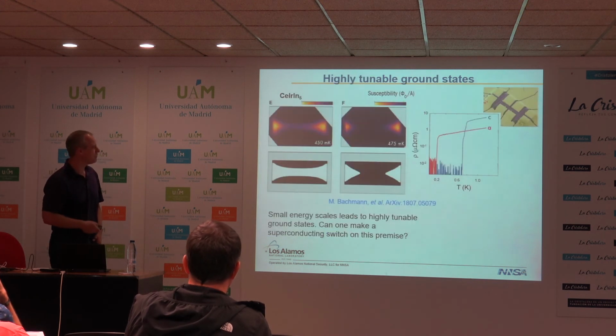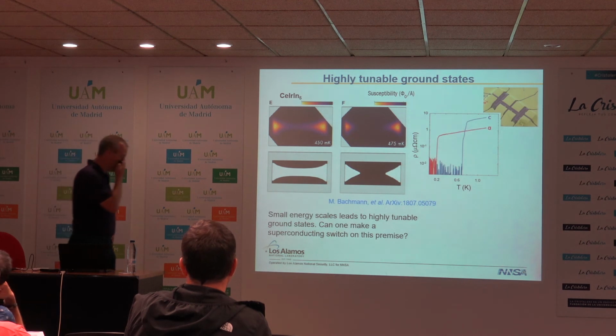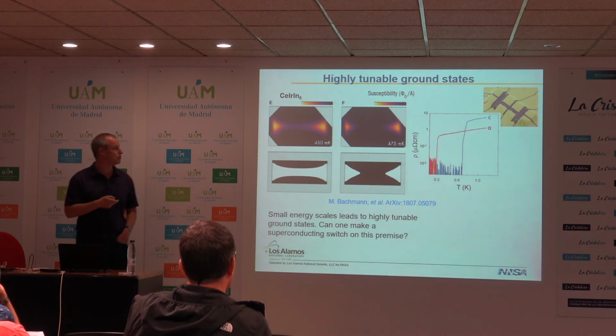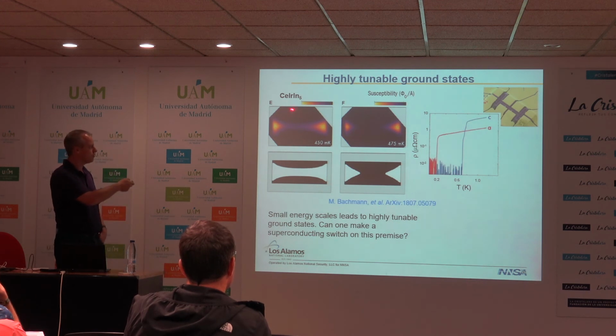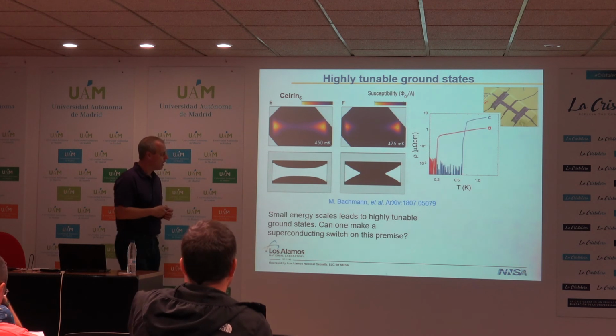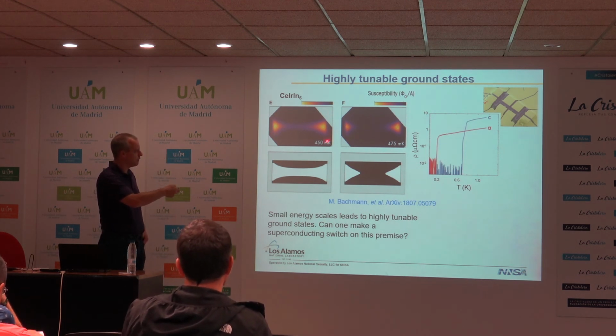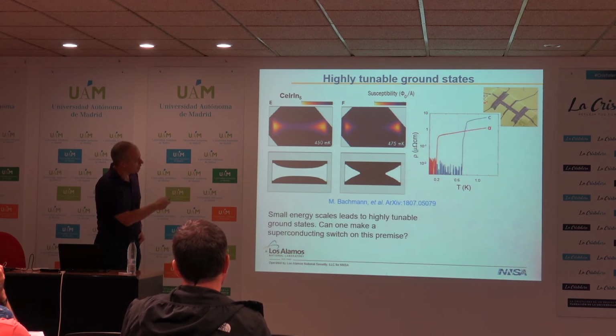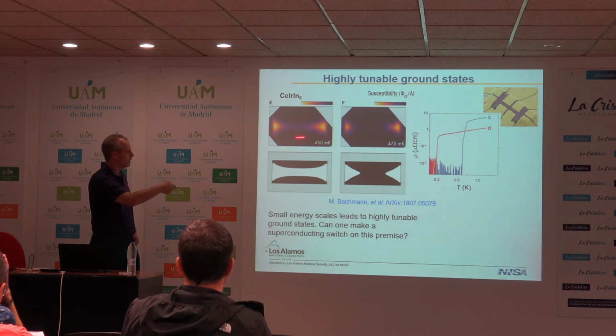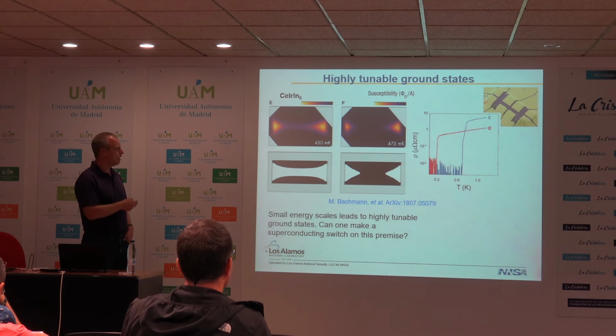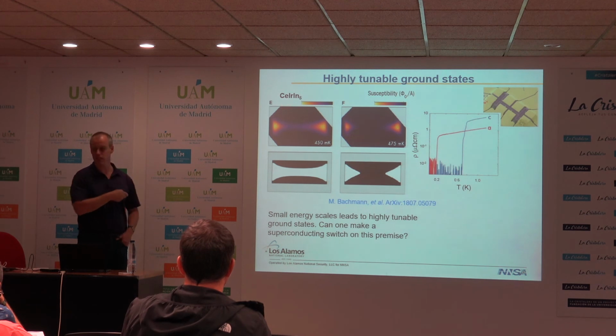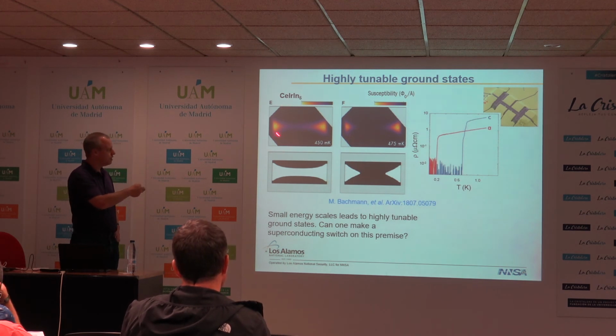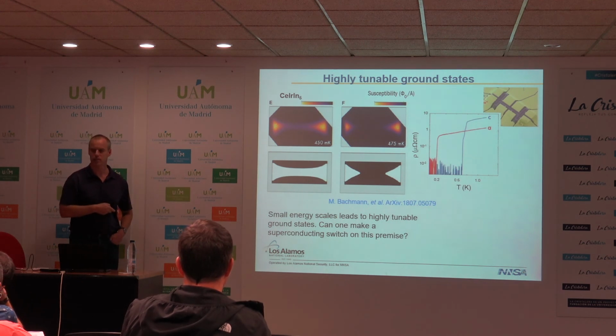Okay, so one thing which maybe is interesting, perhaps from an applied perspective, is these highly tunable ground states. So now I'm looking at another version of the system, CeIrIn5. And this is again one of these FIBed lamellas, so a small rectangular structure. Sorry, there's no scale bar here, but again, this is 20 microns or so. And what was found was, this is some scanning SQUID work that was done by Katja Nowack, where she saw the superconducting response. Now, this is a system which is superconducting in the bulk at 0.4 Kelvin.